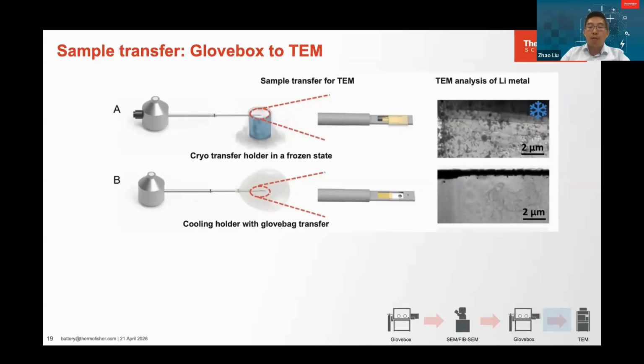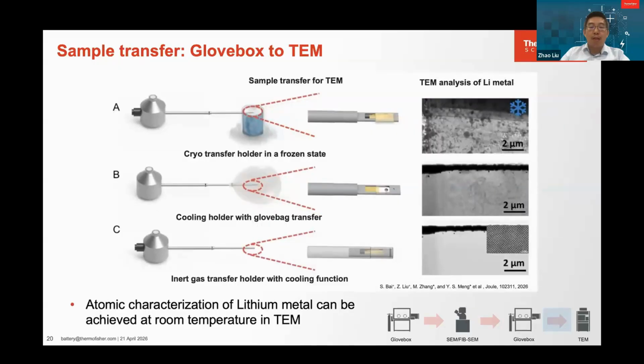So what is the recommended solution in these cases? In our experience, we found that if you have an inert gas transfer holder, where the holder can do the inert gas transfer with the cooling function, when you insert it into the TEM you will get a very clean surface, which you can see in row C over there. And if you can get a very clean, non-contaminated lamella in the TEM, you can even get atomic resolution of the lithium without putting the sample at cryogenic temperature. So the question is why, in past experiments, scientists and engineers always needed to put the TEM sample at cryogenic temperature to minimize the damage.